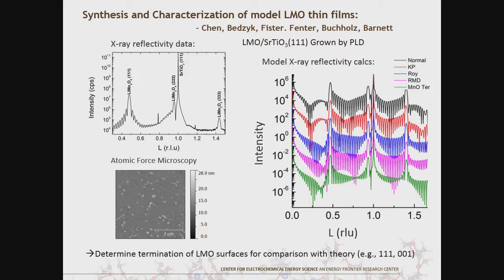You can get nice AFM images, typically flat. The reflectivity data shows these high-frequency fringes, which come from the thickness. Ultimately, this data will tell us about the details of the structure of the LMO surface and how it interacts with the electrolyte. We haven't solved this data yet, but here are some model calculations on the right for the different types of terminations.